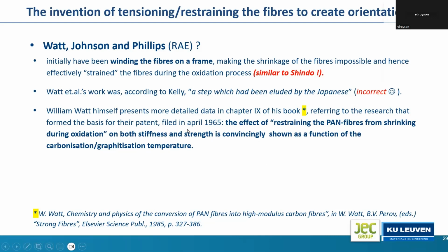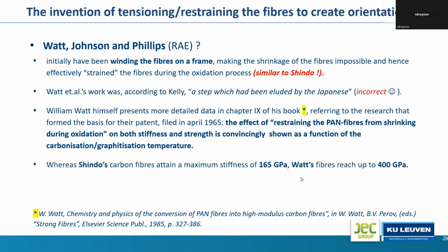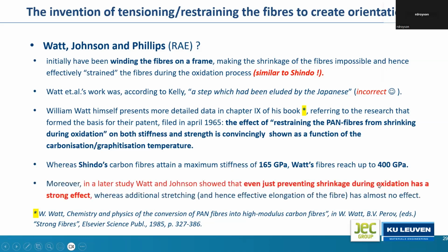Anyway, in the documents related to their patent, they state explicitly the effect of restraining of PAN fibers from shrinking during oxidation on both stiffness and strength, convincingly shown as a function of the carbonization and graphitization temperature. So they were aware that this is important. And by doing that in a more systematic way, and you can read those papers, they reached a stiffness of 400 gigapascal.